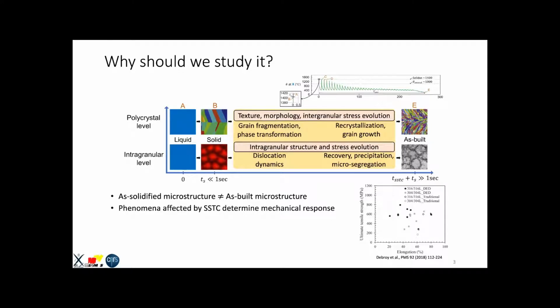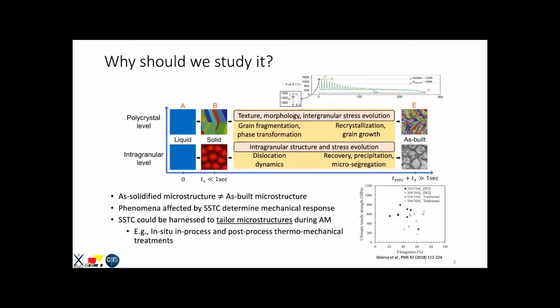And so, for instance, over here you see this tensile strength versus elongation curve showing a large scatter in the mechanical properties from different machines and different materials. And maybe to understand this better, we need to focus a bit more on solid state thermal cycling. Going beyond that, if we understand solid state thermal cycling well enough, then we could harness it to tailor microstructures during additive manufacturing. For instance, we can propose in situ, in-process and post-process thermomechanical treatments during additive manufacturing.